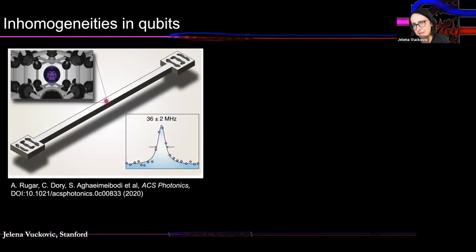And the problem is, again, in the fact that you have to incorporate these individual atoms and impurities inside of a solid in such a way that you don't damage the solid itself. That's why there is a lot of exciting work in Sydney on really doing an atomic force, kind of scanning tunneling microscope arrangement of atoms inside of a material, right? But we're trying to also do it by implantation or incorporation in such a way that we don't damage the environment, because ultimately you want to have your naturally trapped atom or ion inside of a semiconducting or solid environment. And that's very hard to do.